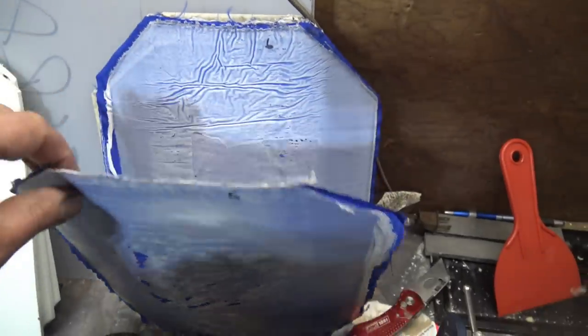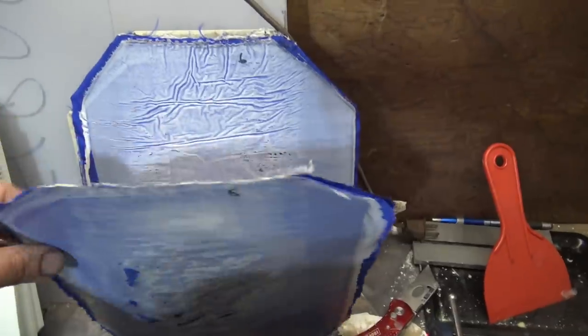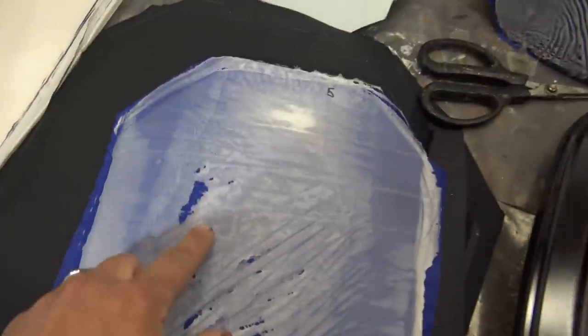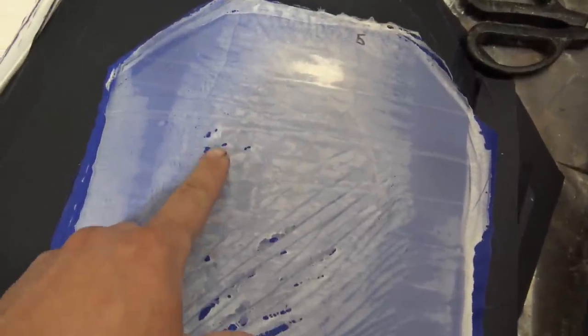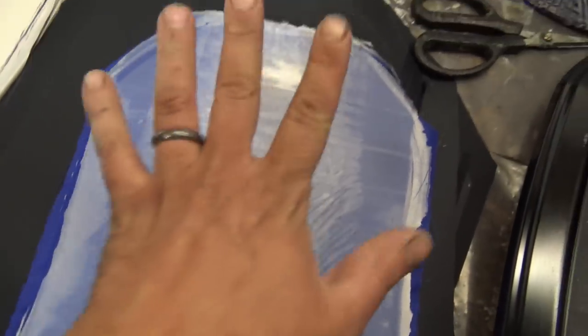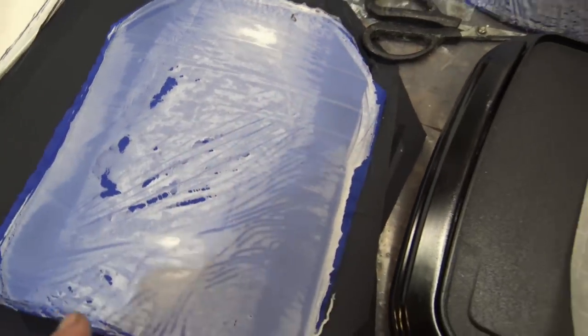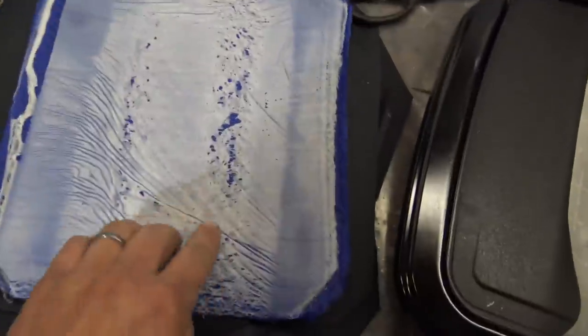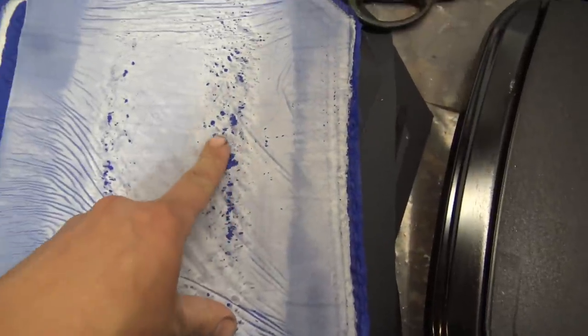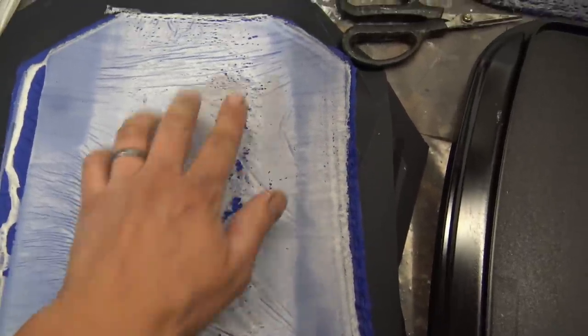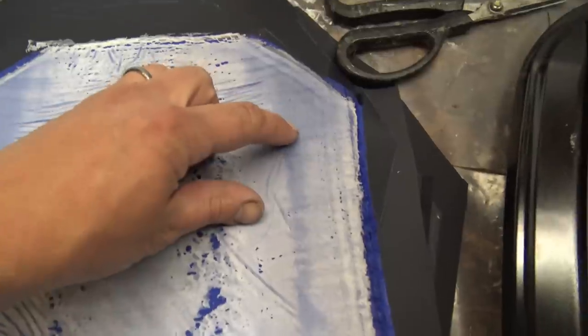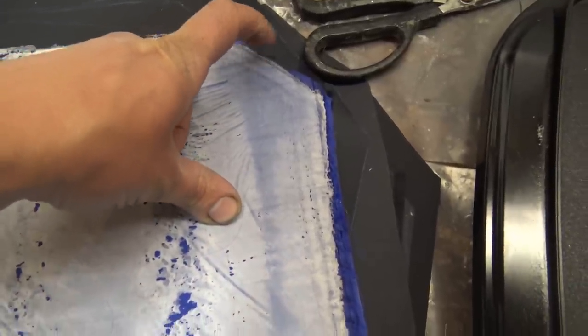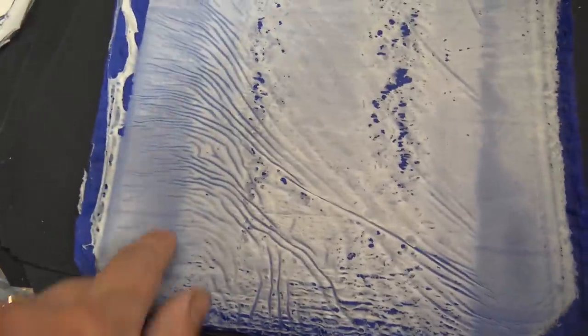Alright, so here's just some of the sample plies, one of 6 layers, one of 5. You can see that in some areas, when the plastic shrank, it ripped. That's alright, because we'll add more layers on top. This is also why I like to do only 5, so that way I can dial in how much plastic is needed. Same effect was happening here. So more plastic is going to be needed. But you can see how well it laminated on the edges, really where the clamping force was.